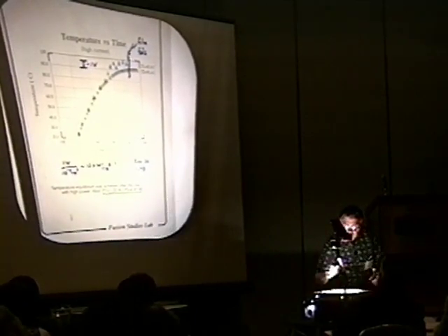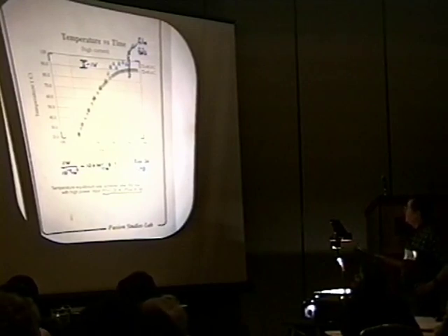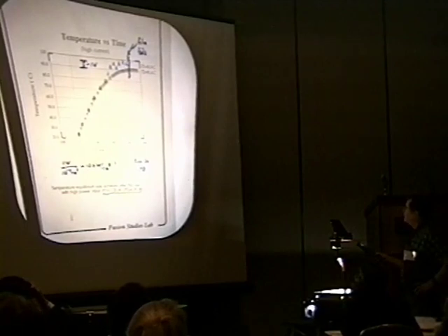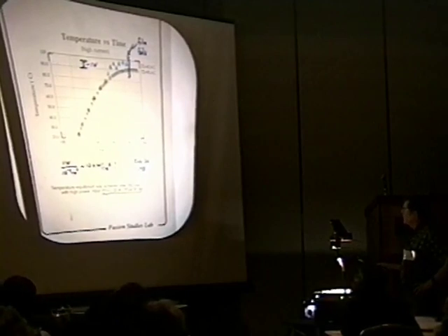Again, if I overlay the result with thin foils, there is a similar effect observed. Deviation begins someplace around 200 minutes. The deviation is much magnified with the higher currents and higher temperature. Hard to tell which is most important in this. Deviations being on the order of a watt, which again, if you consider the small volume of the foils, represents on the order of tens of kilowatts per cubic centimeter in the foil prior to its self-destruction.